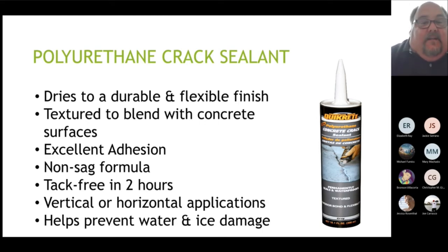So we're talking about ease of use. This is about as easy as it gets. When you've got cracks in your concrete, the polyurethane-based crack sealant is incredible. Polyurethane base, because the poly really bonds and sticks and is very, very flexible. So you won't have to worry about it busting out if you really have an active slab. This one has a little bit of a sandy texture to it, so it matches the existing surface a lot better. And being a non-sag formula, if it's on a driveway, you're not going to worry about it running down the driveway.